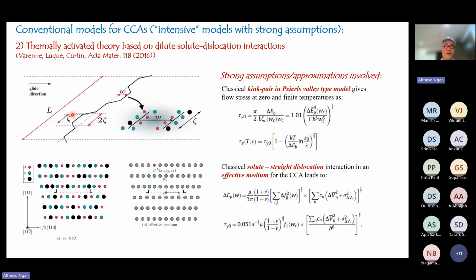Another one would be, for example, from the group of Bill Curtin, where they basically focus on the solute-dislocation interaction, but then they make use of the solute-straight dislocation interaction in the classical literature and bend that into an effective medium to describe the CCA. Again, the model is mathematically appealing, lots of equations in that paper if you really read into it. But it comes with a lot of strong assumptions, particularly the fact that in the CCA every atom can be regarded as solute as well as solvent. So how are you going to specifically define which atom is solute and which atom is solvent? This is a very strong assumption that is involved.